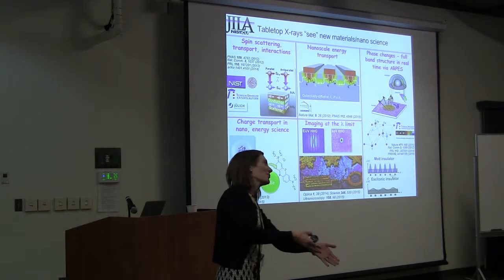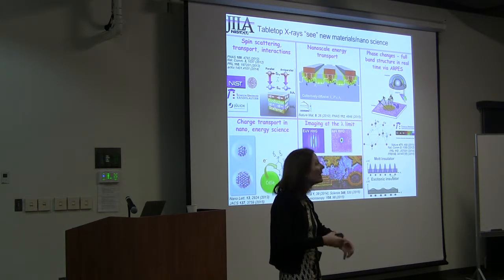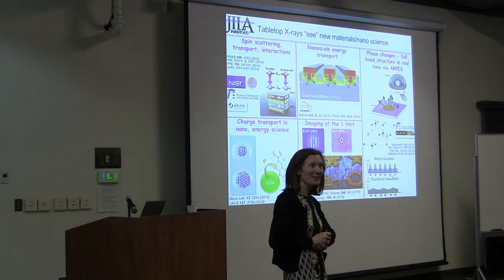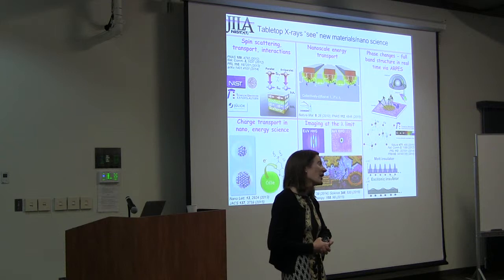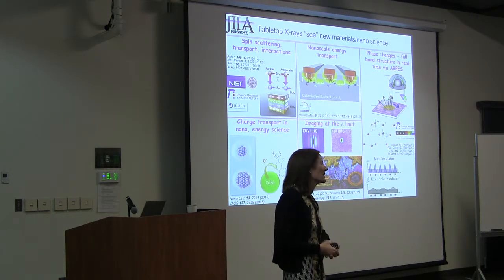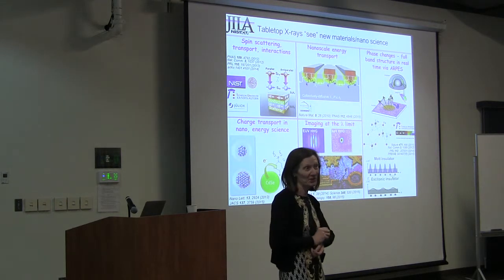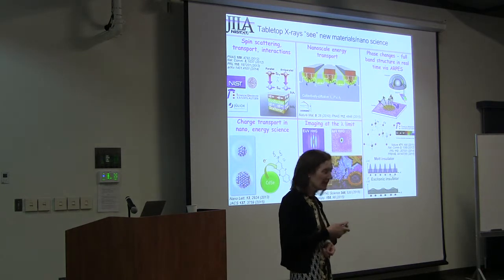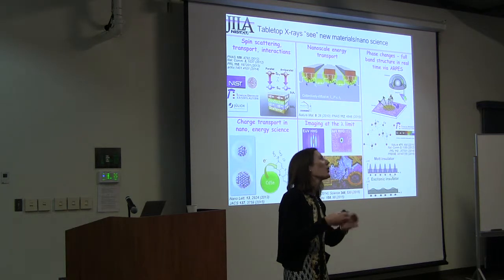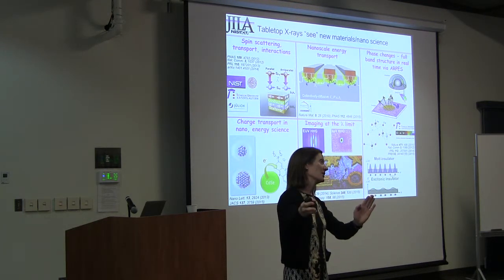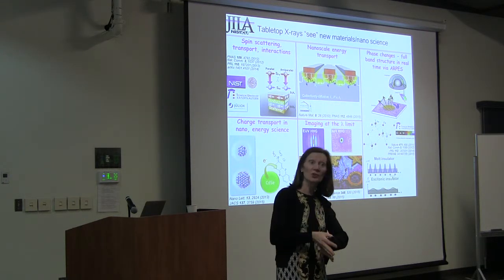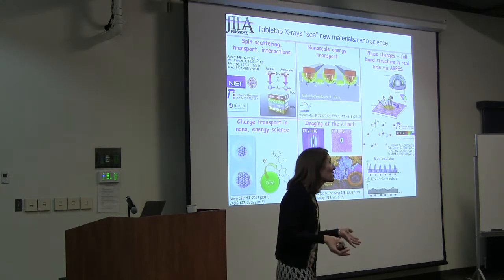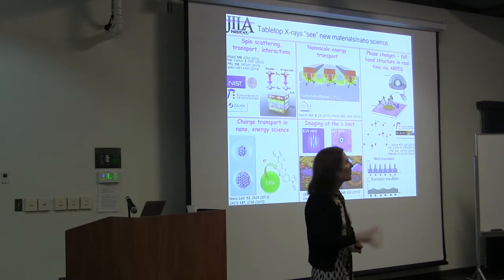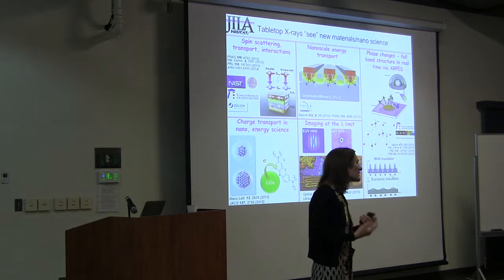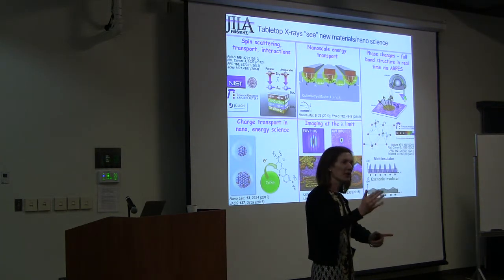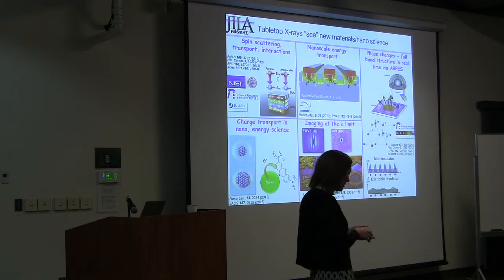Because if you shine the X-ray beam on the sample and you want to look at the photoelectron spectrum of the material, if you pull too many electrons off, and we heard Linda talk about this, you distort the spectrum. So in fact, what you want for photoemission is very high repetition rate, 50 to 100 kilohertz, and very small energy per pulse, and that gives the nicest photoelectron spectra. And of course, because we have time resolution also, essentially it lets you map the whole band structure of the material, because it can probe all the way out to the Brillouin zone edge, which you can't do with ultraviolet or visible light. So you see the whole band structure of the material, and for some of these strange materials like the topological insulators, or these materials that undergo very fast state changes, if you can see both the band center and the band edge, you can actually learn a little bit more about the physics. So that's one killer app.